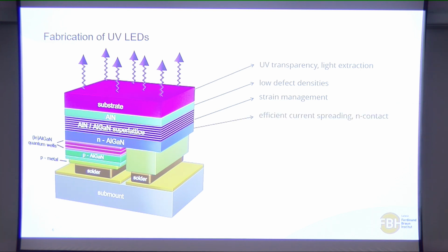And then you come to a current spreading layer, which is the n-contact layer. There you want to have really high conductivity in this layer so that you have a low operating voltage of the device. And then you come to the active region, which is basically indium aluminum gallium nitride quantum wells. And here it's really important that you look at aspects such that the carriers are really confined in the region. You have also sometimes polarization of the light, which I will explain a few slides later.